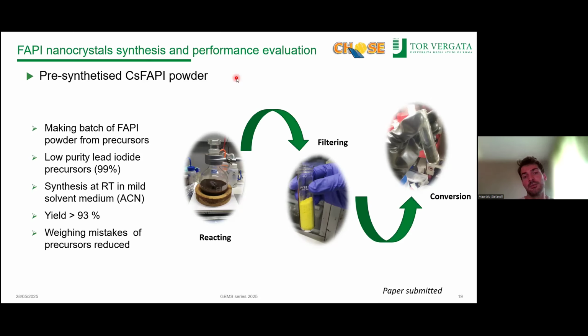So basically what we did is we put the cations in ACN and let them react with the lead iodide at low purity for 24 to 48 hours at room temperature. Then we filter off all the crystals, which in this case are in delta phase, and then we convert them in an oven to the alpha phase. Once we got these crystals, they are already in alpha phase. They are stable for months in an inert environment and can be weighed as a normal powder. Then, obviously, we can use our solvent system to get the ink solution.